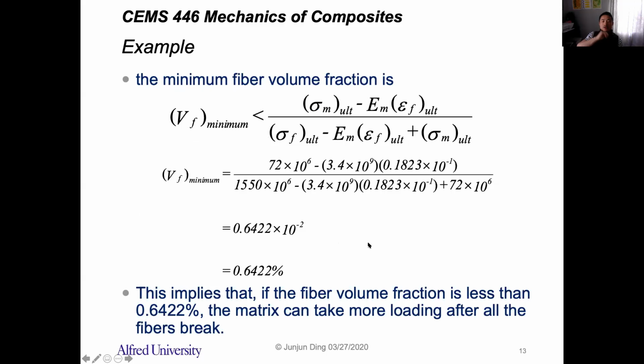Okay, so to calculate the minimum fiber volume fraction, we simply apply this equation, or you just use that relation between the ultimate strength of the failed composite and the ultimate strength of the composite, right? To see, before the fiber fails, which one is larger, right? So based on this equation, we find the minimum volume fraction of the fiber is around 0.6422%.